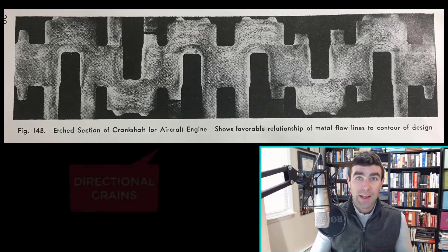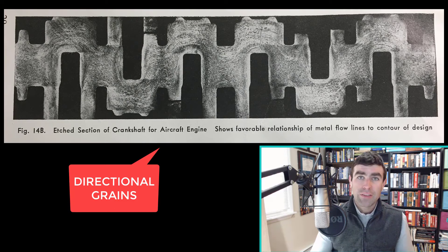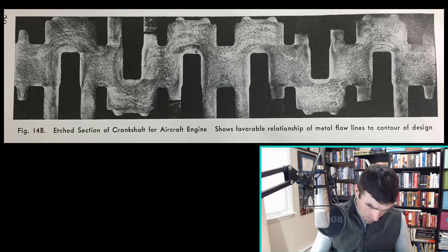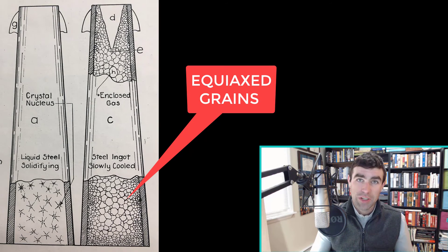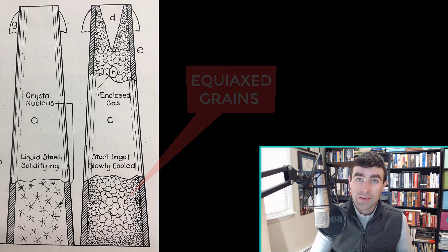The last topic in this section is cold forging. Cold forging uses the same basic techniques as hot forging but the material is at room temperature, so you get that directional grain structure. If you have a gear blank or a bolt head, the grains follow where you need the strength instead of being equiaxed like a casting or being cut off as if machined. Common uses for cold forging include bolt heads — called cold upsetting — and screw threads, which are typically rolled at room temperature. This gives greater strength but less ductility than something that's been machined or cast.